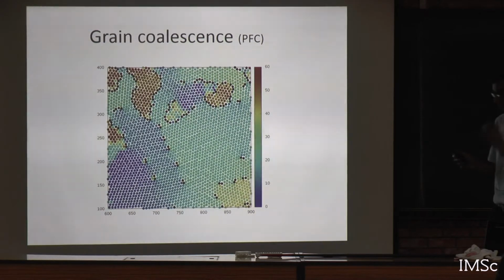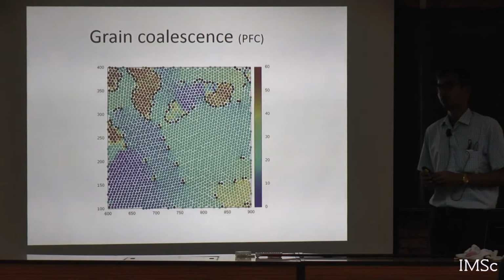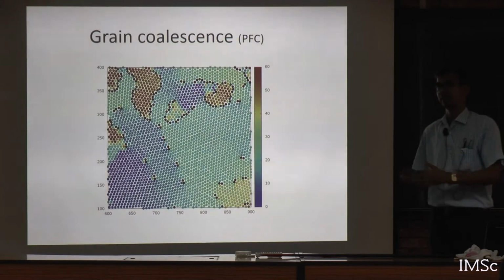Now, all this happens in some intermediate range, because if the shear is very small, then you do see such movements, but it happens much more sparsely. It is almost close to the equilibrium regime where things are happening, but very slowly. If you do it too fast, near the wall the layers start to slide, and in between you find a single crystal. So this is somewhere intermediate. Does the system ever melt into a liquid? No, it always crystallizes rather.